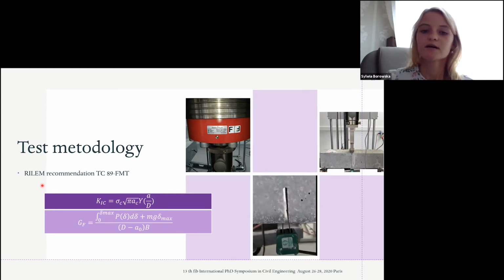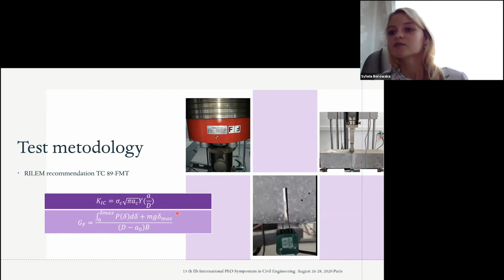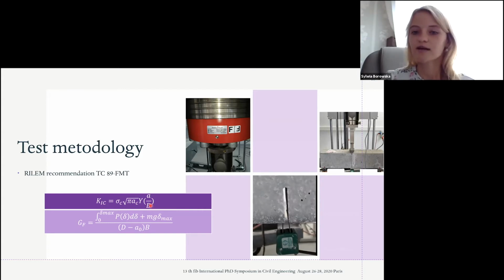The force was applied in such a way that the max load was reached within 5 minutes from the start of the test. The load was carried out by adjusting the displacement of the piston. The crack mouth opening displacement was measured using a clip extensometer. We can see 2 formulas for stress intensity factor and energy absorbed during the fracture process,